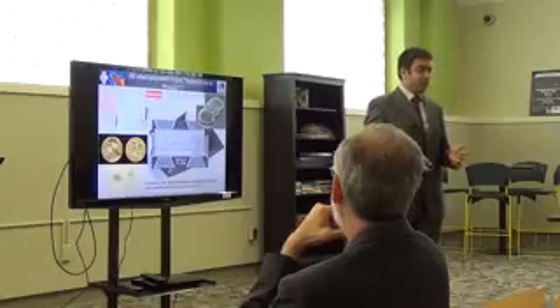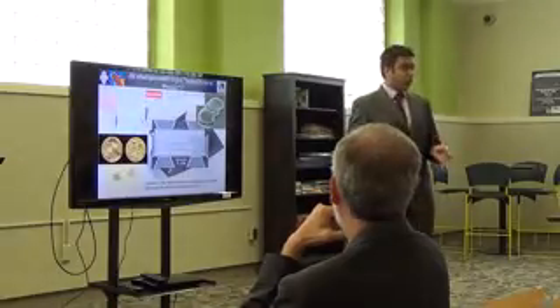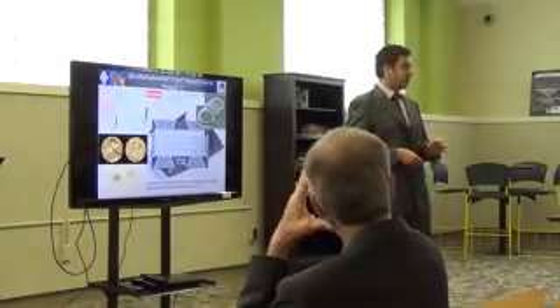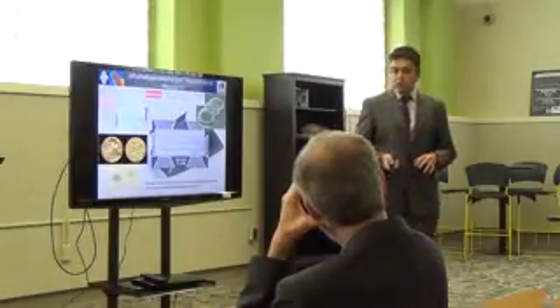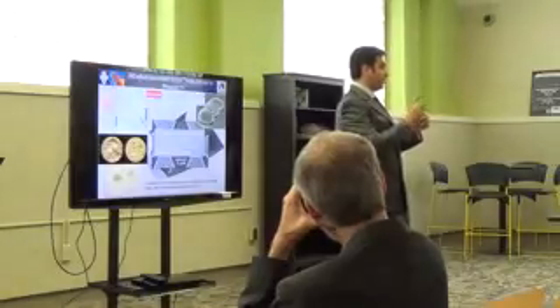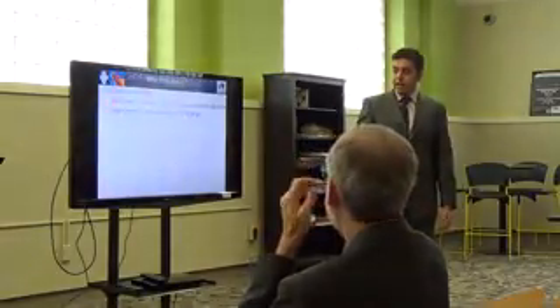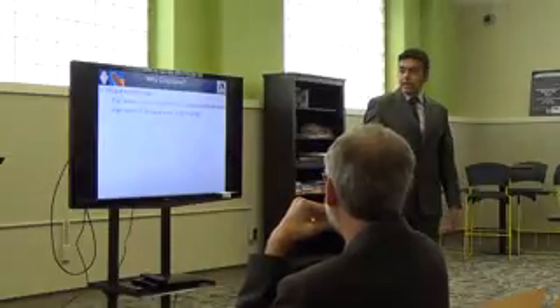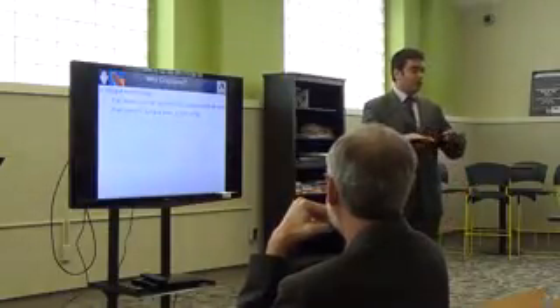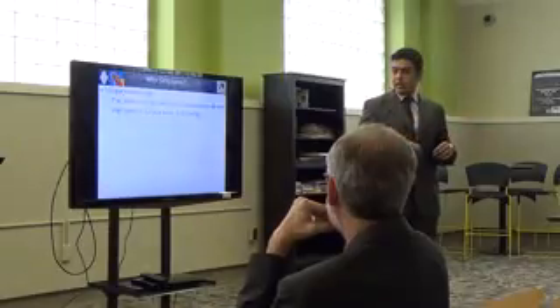Actually, this technique was very nice and simple, and it worked for graphene and some other layered materials, but it doesn't work for everything, because it needs very weak bonds between the layers to separate them mechanically with Scotch tape. Actually, why is graphene interesting? Graphene has a unique morphology. They are flat, so you can make micro devices out of them.